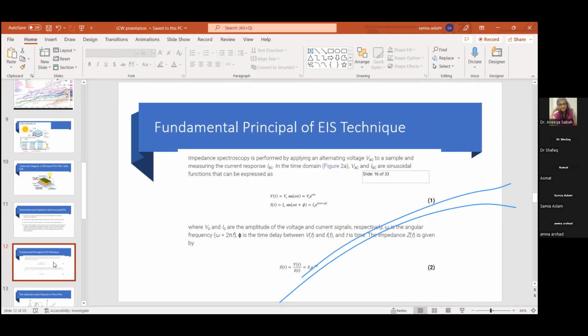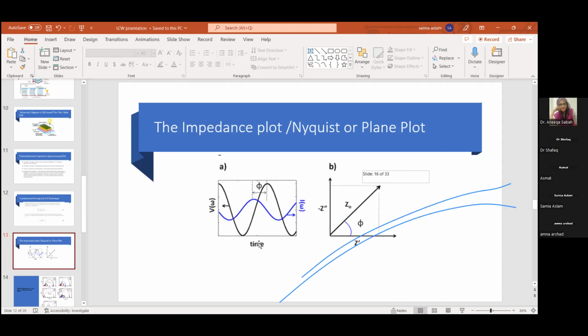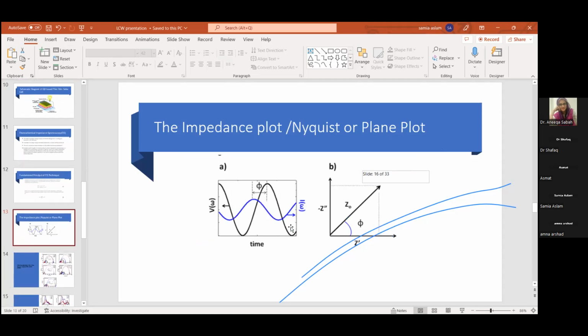And what we plot is basically the impedance plot, which is known as the plane or Nyquist plot, which represents the impedance of an RC parallel circuit at a certain interface of the solar cell. So in this way, this works, and here is what we are going to give as an input, and what we are going to have as an output is an impedance plot.